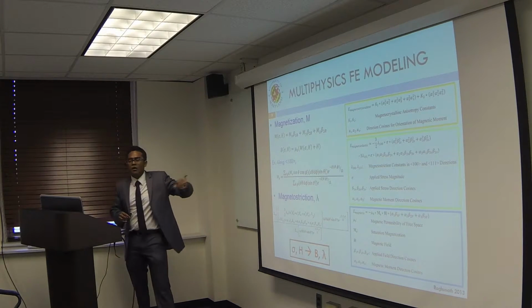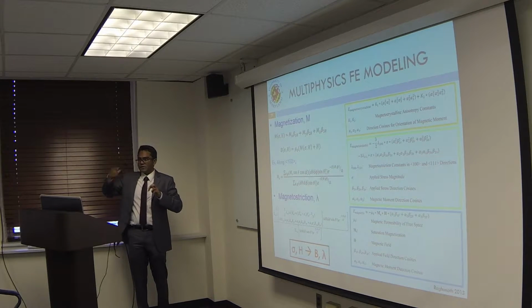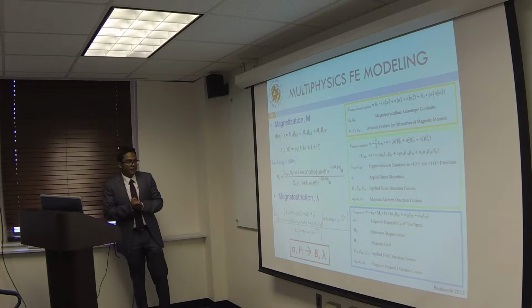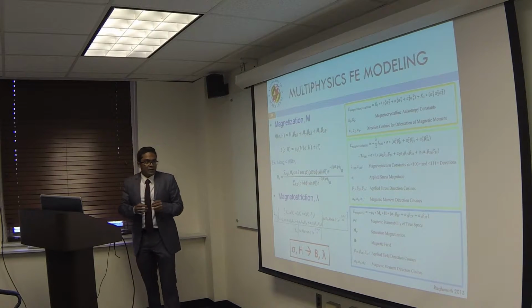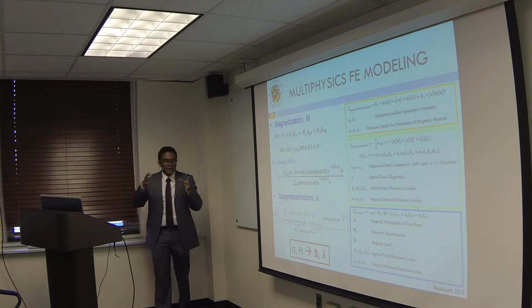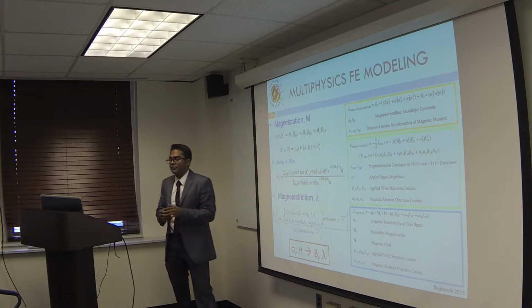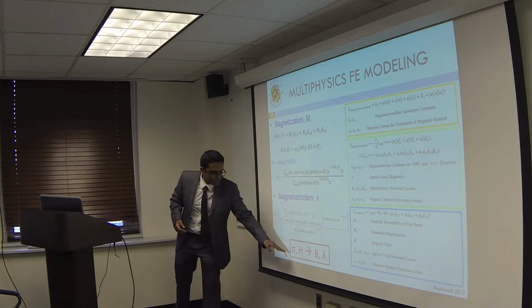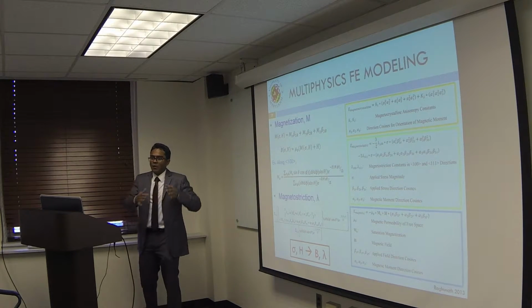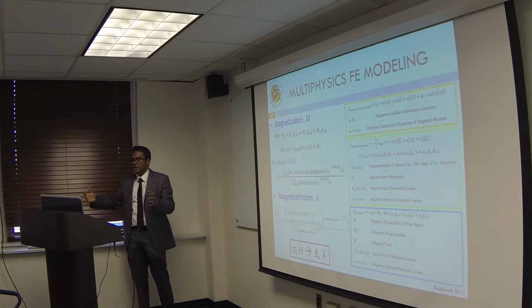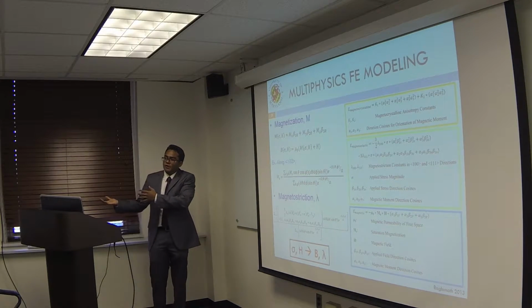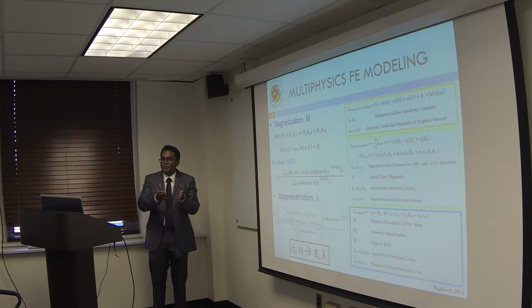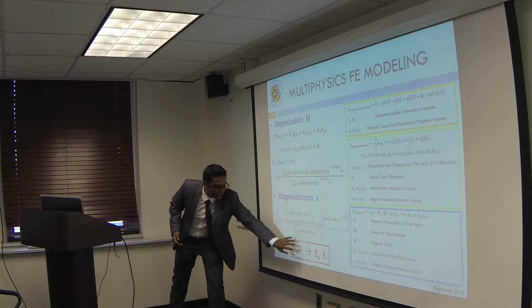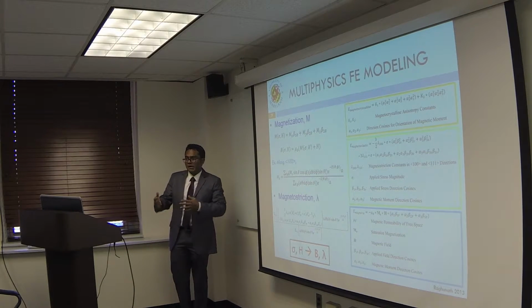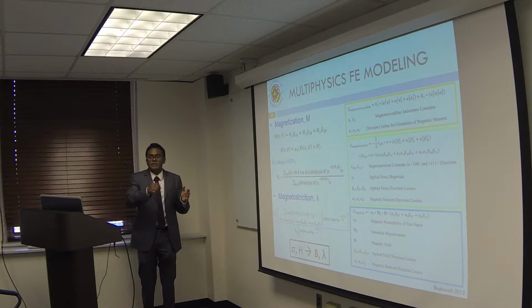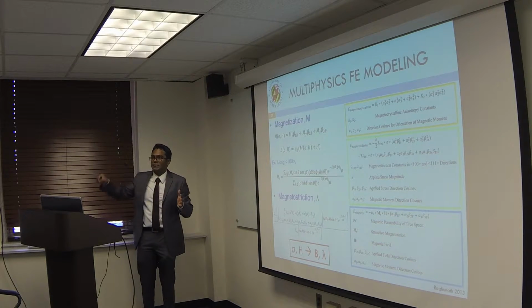It used the same energy formulation, but since it's an iterative process, you can vary the magnetic field and get varying values of magnetostriction. So we had an in-house code which could predict the values of magnetic strain and change in magnetic induction for any values of stress and magnetic field that we give as inputs. Once we build up this library, what COMSOL does is you give it a geometry, and then you ask COMSOL to go back into the library and pull out values depending on what inputs you give to the system. So if I know the value of magnetic fields that I'm going to be giving to the system, COMSOL goes back into MATLAB and pulls out the MATLAB library, and then it pulls out values and plots it for us.